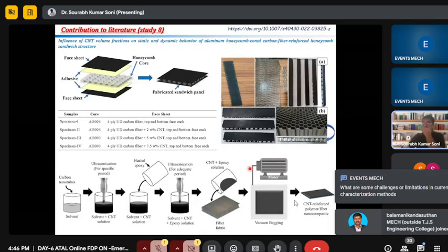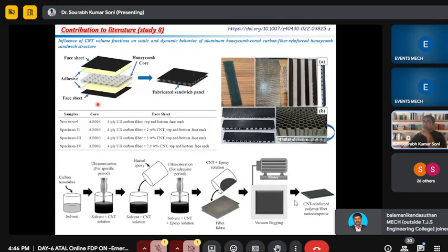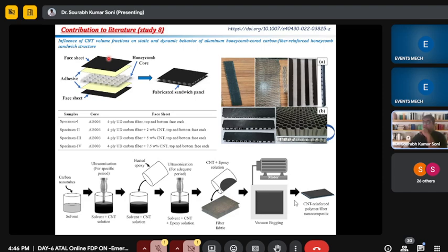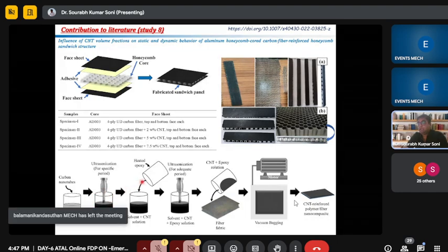Apart from metal specimens, I have investigated carbon fiber and glass fiber hybrid composite specimens also. We have prepared a sandwich panel with the help of a honeycomb structure. Here you can see the top layer is carbon fiber, the bottom layer is carbon fiber. In between, we have fixed the aluminum honeycomb structure to analyze vibration and flexural behavior. This is the route we followed for preparing the hybrid nanocomposite. First, we mix the carbon nanotube in the solvent, then sonication for a certain period, then heat the epoxy.